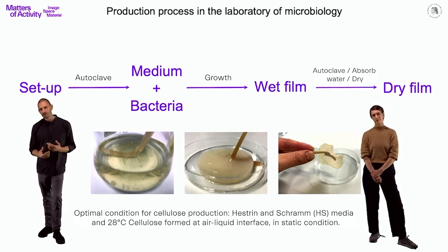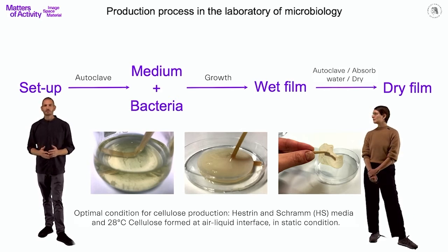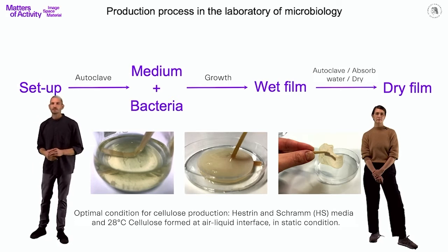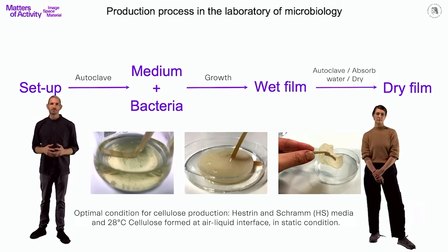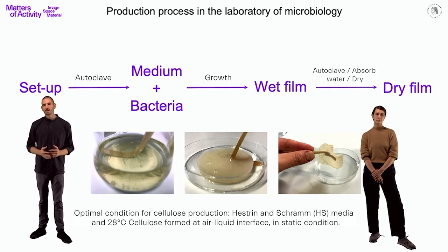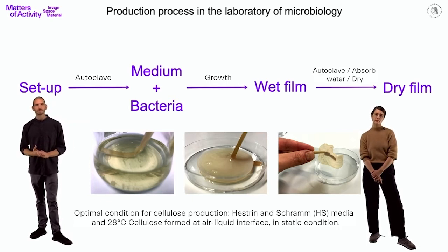Formation of bacterial cellulose generally occurs in several stages of materiality. The first one is when the biofilm is microbiologically active and the bacteria are permanently producing cellulose. The second one is when the hydrogel is completely formed and the growth slows down or stops. In the third stage, the hydrogel is dried and only the cellulose containing the residue of the medium remains, while the active growth has completely stopped.